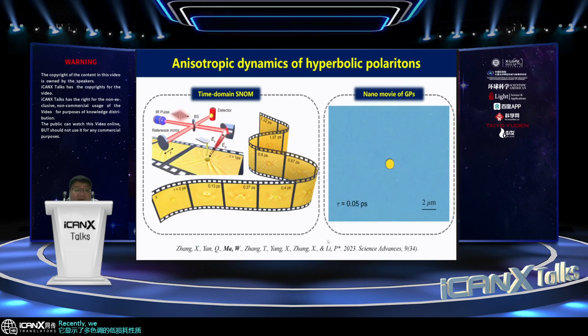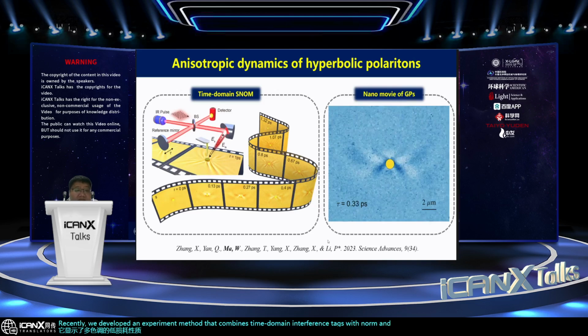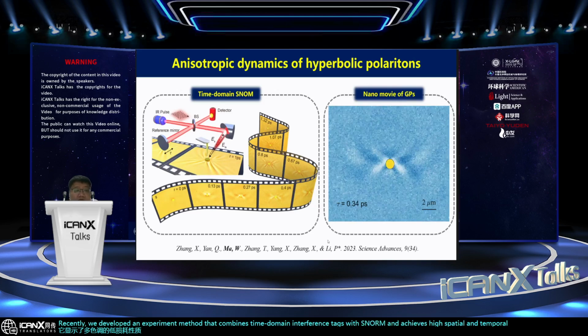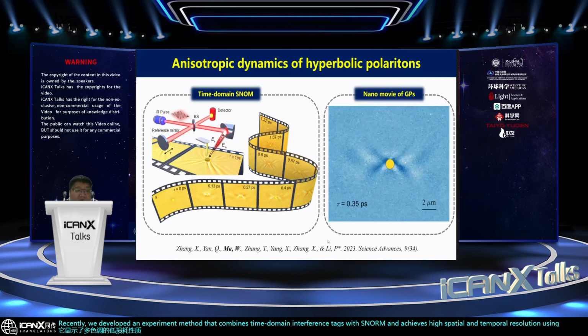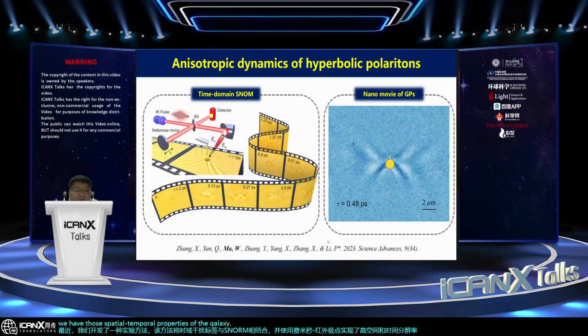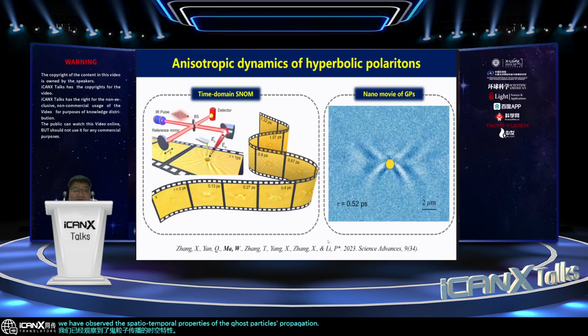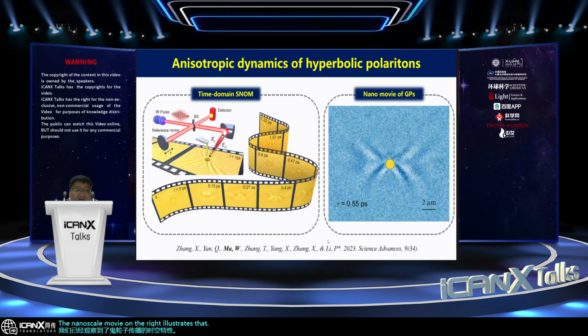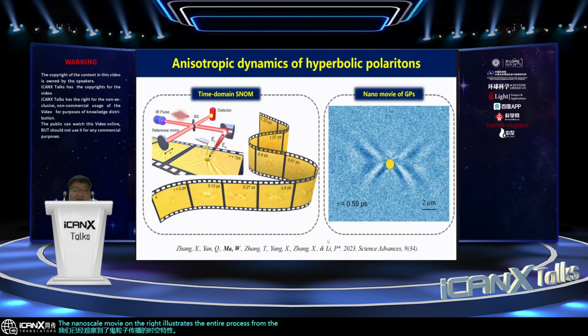Recently, we developed an experimental method that combines time-domain interferometry with SNOM and achieves high spatial and temporal resolution using a femtosecond infrared pulse. We have observed the spatiotemporal properties of the ghost polaritons' propagation. The nanoscale movie on the right illustrates the entire process from the generation of the ghost polaritons to their propagation and their decay.